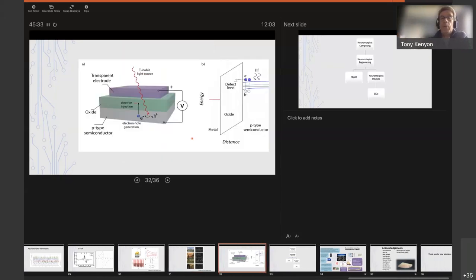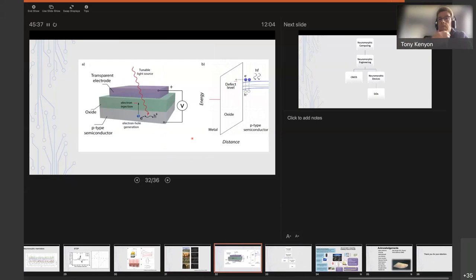We can go a bit further and we can see that if we now take one of our devices and we apply a voltage which is too small for there to be that sudden jump, that formation of the filament, so the voltage that we've applied isn't enough to start moving the oxygen and separating it from the silicon. But we apply at the same time a stream of photons, we shine light on the system, and that light is absorbed here in the semiconductor at the bottom. Well, when the semiconductor absorbs light, what happens is you generate carrier pairs, if that light has sufficient energy, if it's above band gap, to produce those carrier pairs. You produce carrier pairs, so you produce electrons. And if there's a small bias applied across this oxide, if you put the positive bias on the top here, negative bias on the bottom, those electrons will be pulled into the oxide.